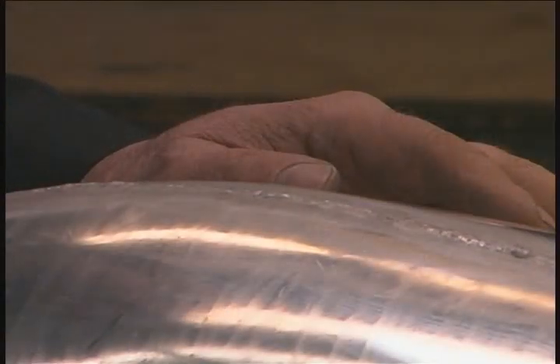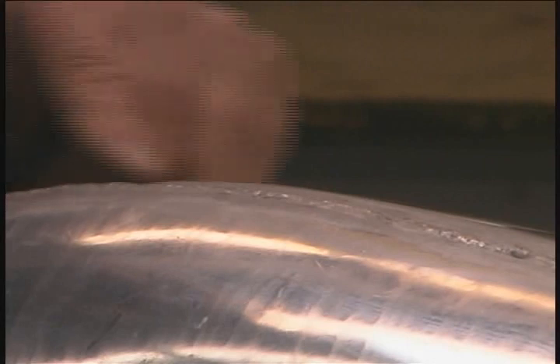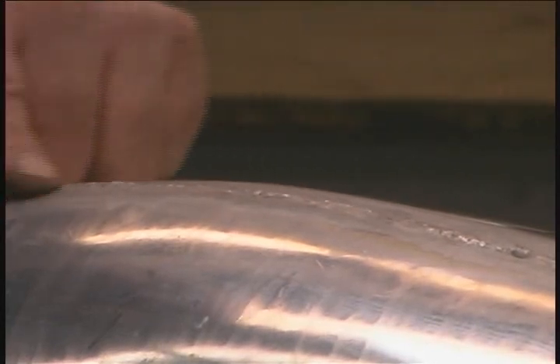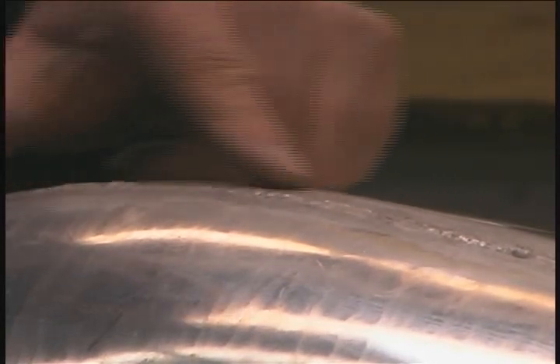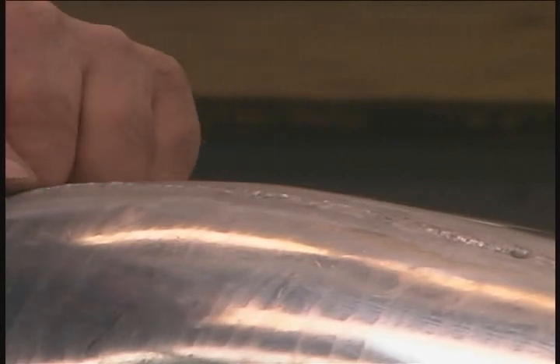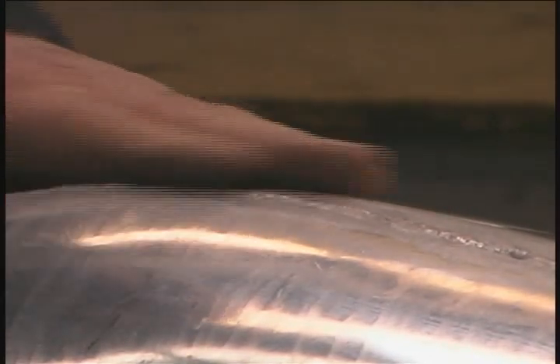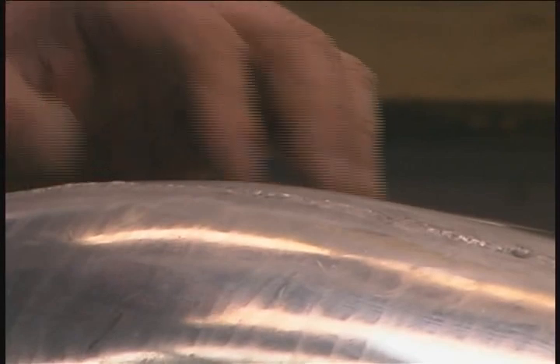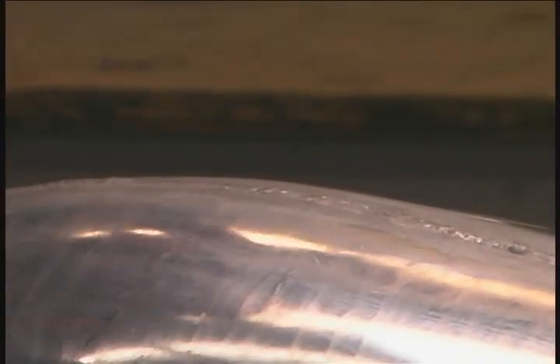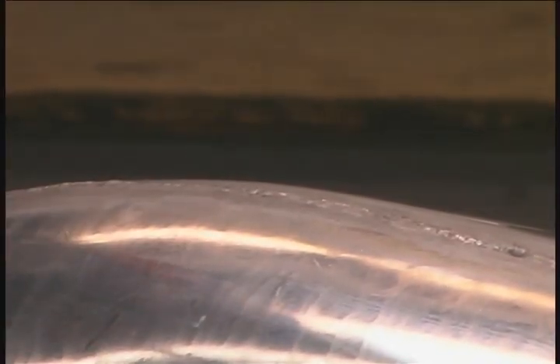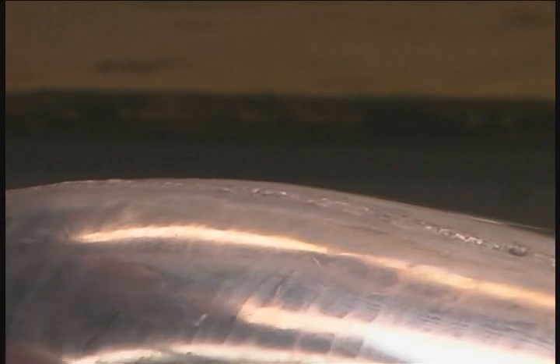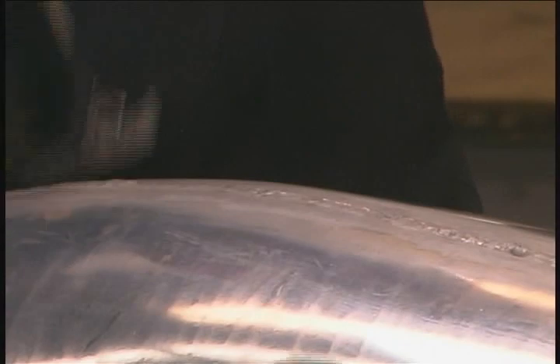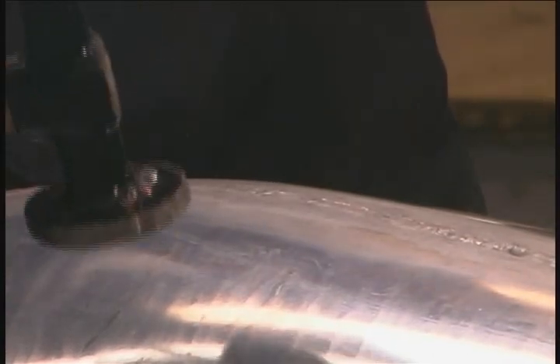Okay, so here's our finished weld. You can see it's come out to be fairly uniform. And the next step is I'm going to use a hammer and dolly to hammer this weld down flat. And you'll see that it will go absolutely flush, both inside and outside. And I'll be using a lightweight hammer for this with a relatively low crown face and my favorite dolly, an egg dolly. And I'll place the dolly under the metal, press up really hard, and then hammer on the weld until it flattens out.